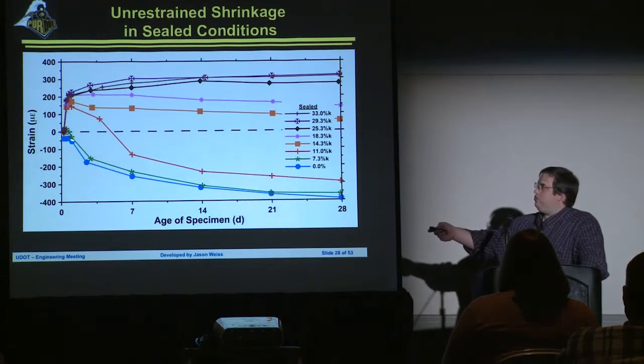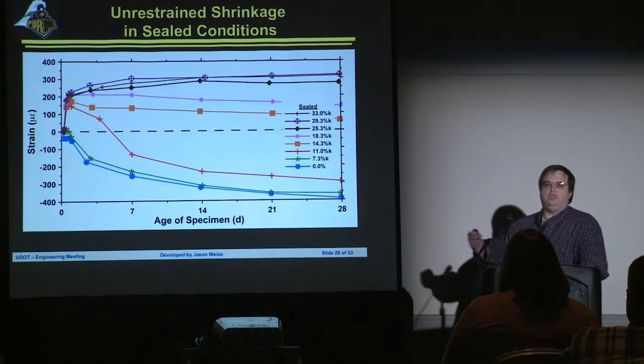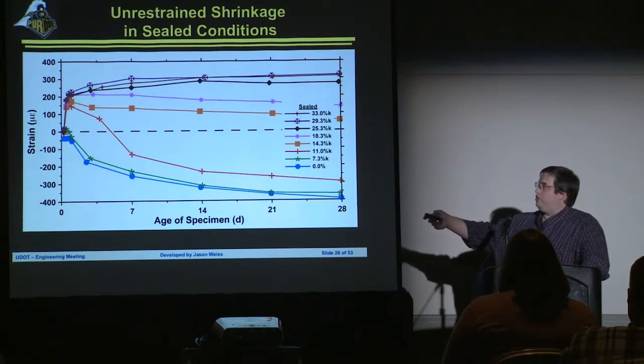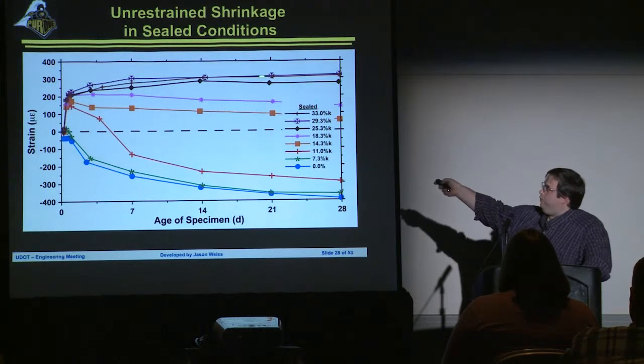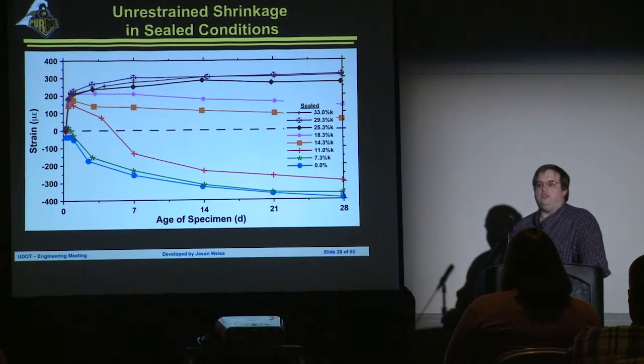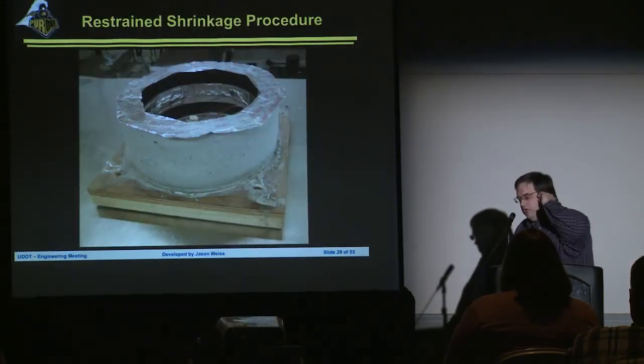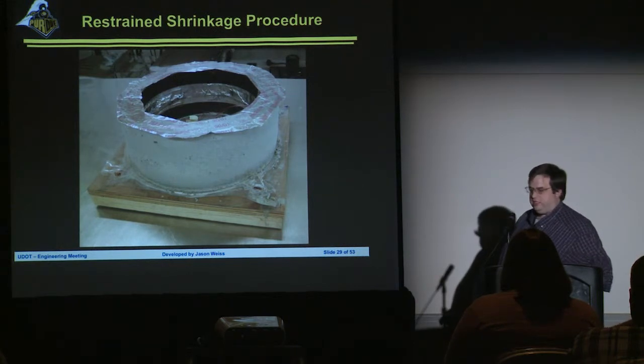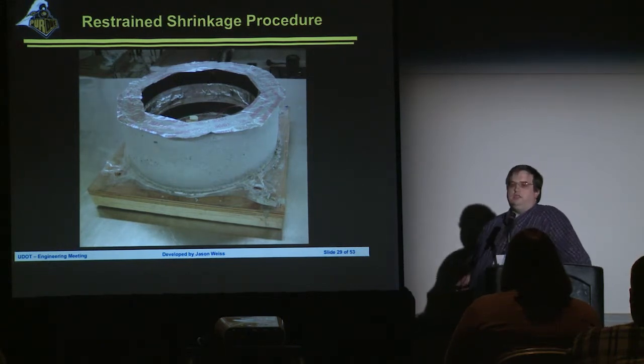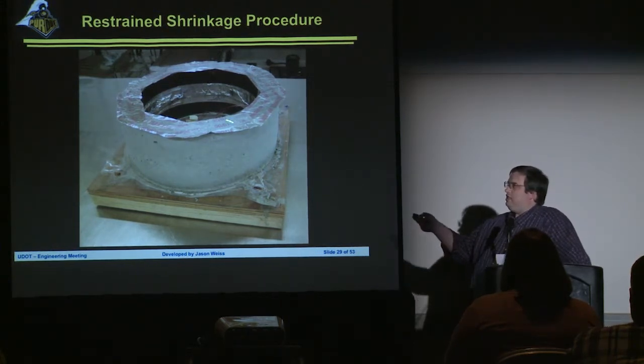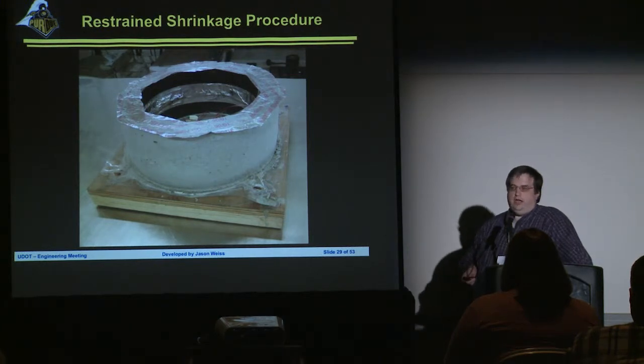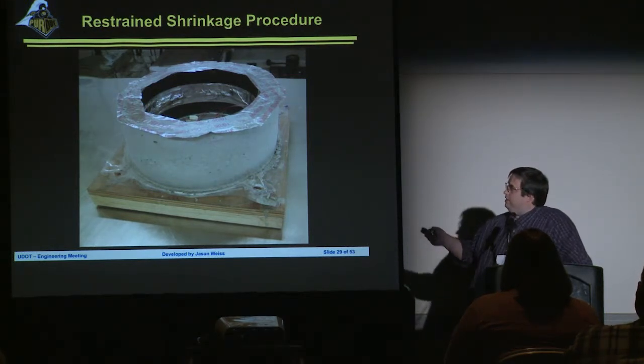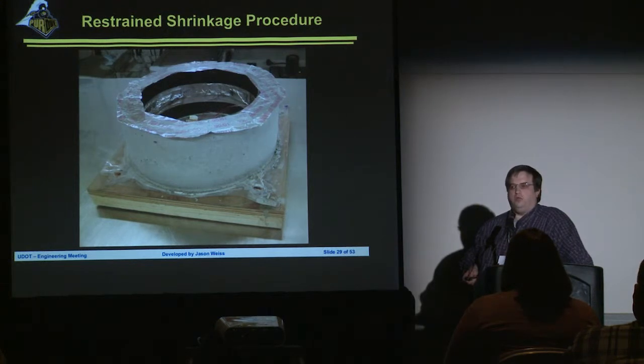Okay. With internal curing, we get a slight expansion because of the release of water. Right? We know that it swells. And then what we'll see is if we put enough lightweight aggregate in the system, we essentially don't have any of this shrinkage. All right, so what does that mean when we start to look at this? Well, here's where we start to look at a slightly different test, and I'm going to stretch our imaginations a little bit. This is a test technique that's called the ring test. All right? Obviously, you look at this and you say, aptly named, it looks like a ring. All right? What is the ring all about?